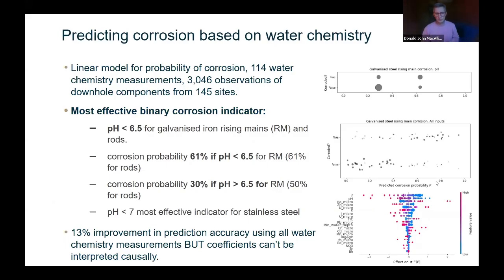Then what we did was build a sort of linear regression model to predict the probability of corrosion based on a number of different variables. We looked at a number of different pH thresholds, including pH less than 6.5. We looked at each of the corrosion indicators that I've just shown you, the Ryznar, the Larson-Skold, etc. And we also looked at, if we put all of our water chemistry results in, including chloride, sulfate, salinity, does that improve our predictions? We had a very large data set of more than 3,000 observations of downhole components from our 145 sites, so we had good statistical power to be able to do these predictions.